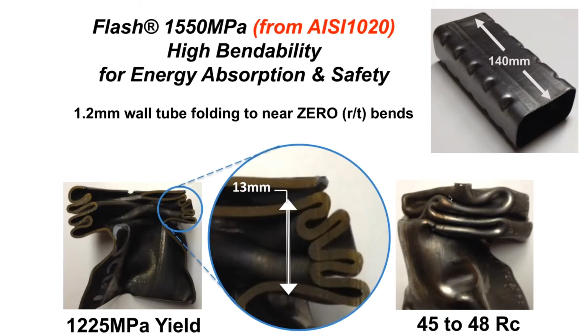We started out with a round tube about 140 millimeters long. We formed it in a little stamping die to put the dimples in it and turn it into a rectangle. Then, very unceremoniously and non-scientifically, we put it in a mechanical stamping press and smashed it. What's interesting is if you look at the inset circle, our material with 1,225 megapascal yield, 1,550 ultimate, and 45 to 48 Rockwell C is actually bending nearly like a sheet of paper without cracking.